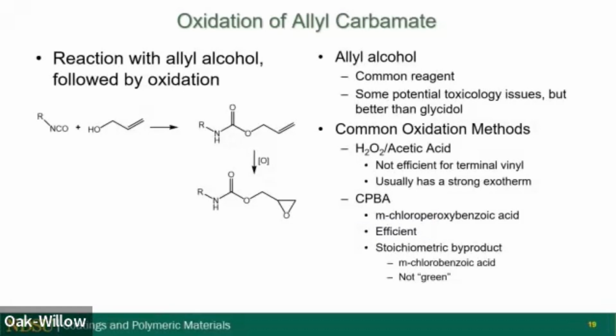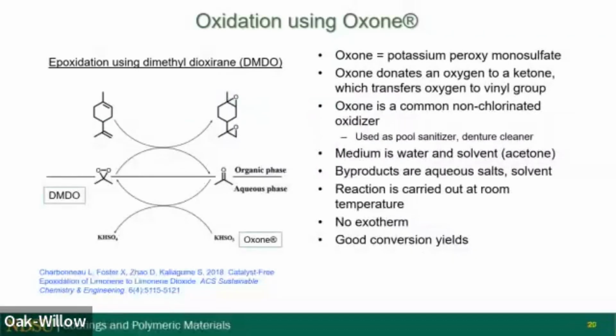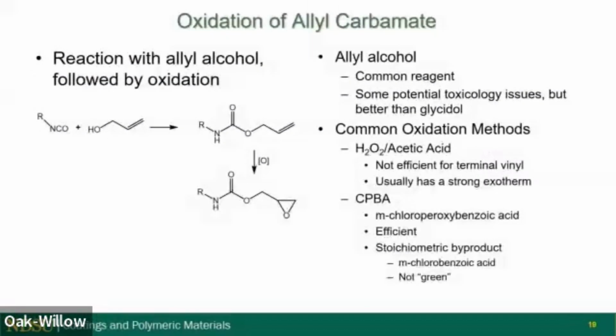And so I had a very smart postdoc at the time, and he said, well, can we put allyl alcohol on the urethane and then react that with oxygen to form the epoxy? And so, you know, we thought that's a better approach, but how do we do this epoxidation? There are current systems out there. The traditional peroxide method isn't good for terminal double bonds. And mCPBA, you have a stoichiometric byproduct, so it's not very efficient synthesis.